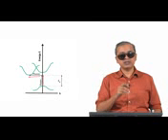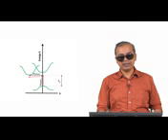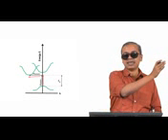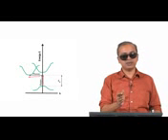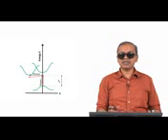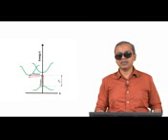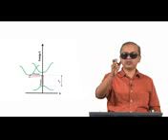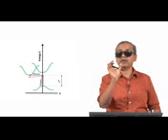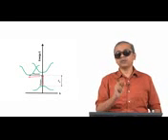So it's a two-step process, as I said. The incoming photon E equals h nu pushes it up in energy, and then a lattice vibration, which is referred to as a phonon, pushes it to the other direction, and that is how you get the transition to complete. Okay, and each of these are statistical. There is no guarantee that once the h nu pushes the electron up, something will automatically move it to the available site. There is a probability that the h nu will push the electron up, and there is another probability associated with the phonon being available at that exact instant to push the electron to that region. So you have two probabilities here.